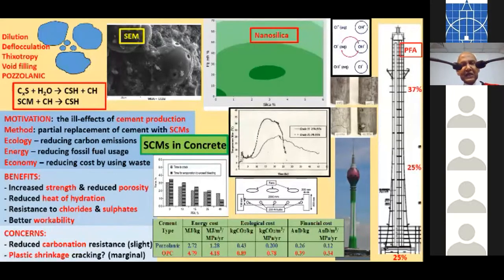So, some of the newer things that are being done here, which once again we have done in our laboratories, now the use of nanosilica together with this fly ash and this cement. Now, why do we need nanosilica? Because now the intention is to reduce the ill effects of cement production. So instead of using just about 30% of fly ash, can we use 50% or even 70% of fly ash? If you use such large percentages of fly ash, then of course your performance will go down.